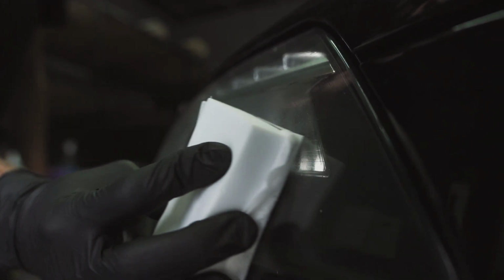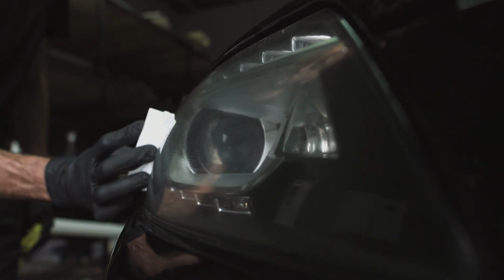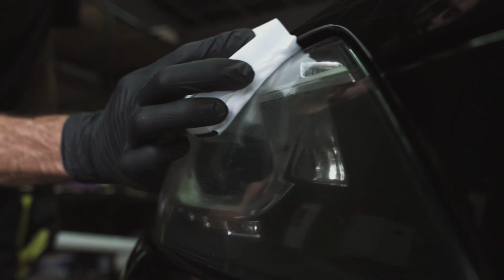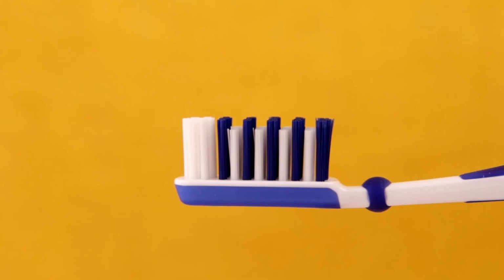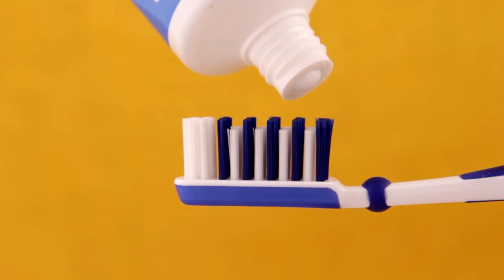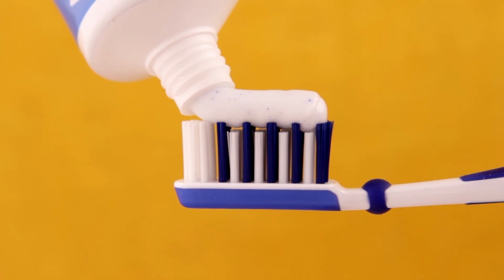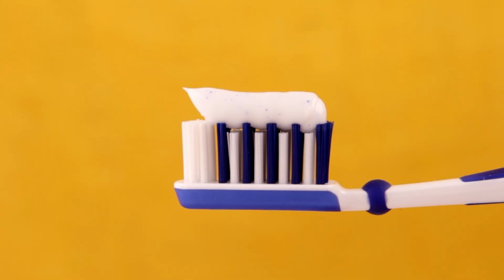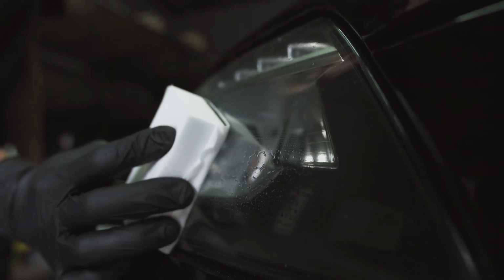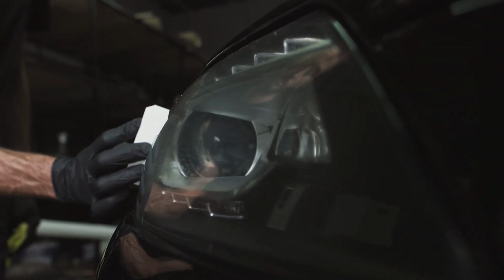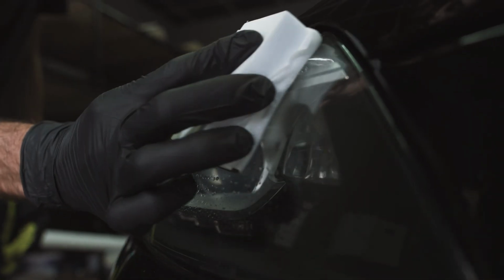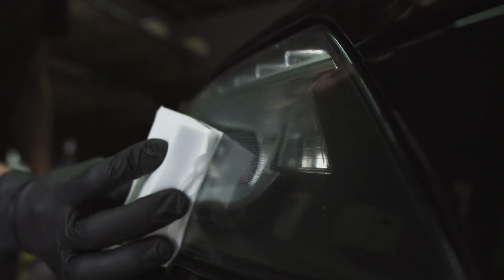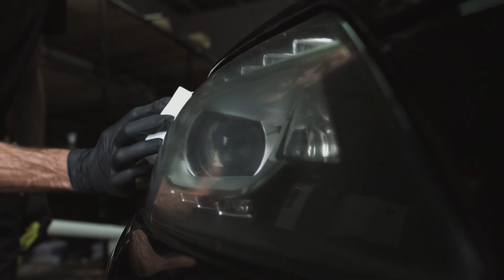The problem is that the headlight of your car is not of glass, like in the vehicles of the 80s, but of polycarbonate, a thermoplastic polymer extremely resistant to impacts but very sensitive to chemical and mechanical abrasion. When rubbing toothpaste, you are creating thousands of micro grooves in the surface. Yes, you eliminate the yellowish layer of superficial oxidation, and the headlight seems clean, but you have left the plastic with an alarming microscopic porosity. You have destroyed the original factory sealing.